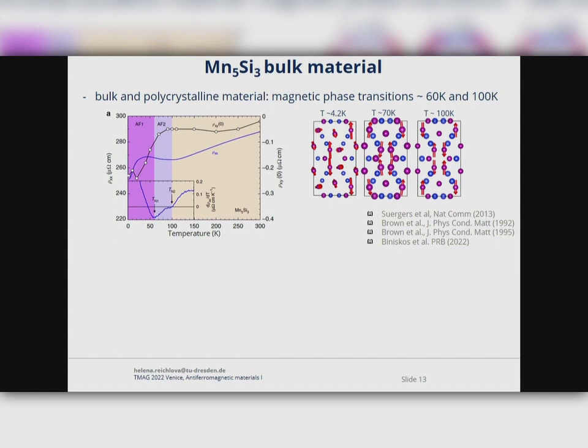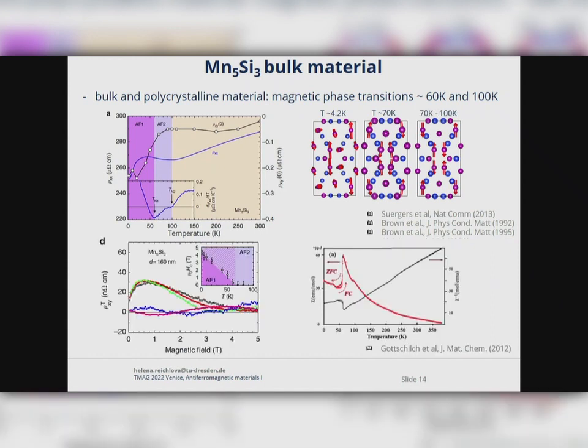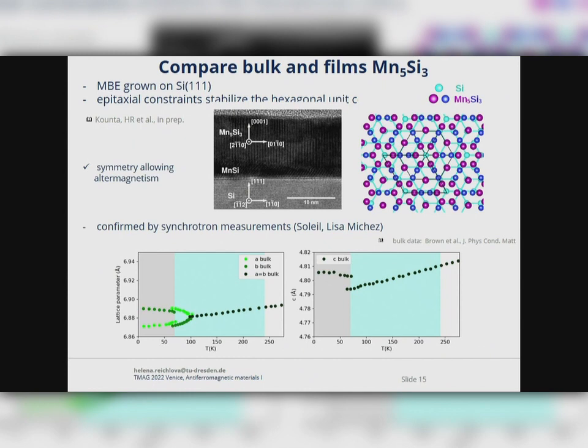And they are associated also with structural transitions, so the hexagonal to the orthorhombic and monoclinic crystal structure. These bulk materials were well studied by various techniques, which confirmed all the transitions, and also the polycrystalline films were fabricated by Christoph Sürgers, and he showed that this non-collinear phase at low temperature leads to a topological Hall effect. And now we prepared thin films which were epitaxial and which were grown on the silicon 111 substrate.